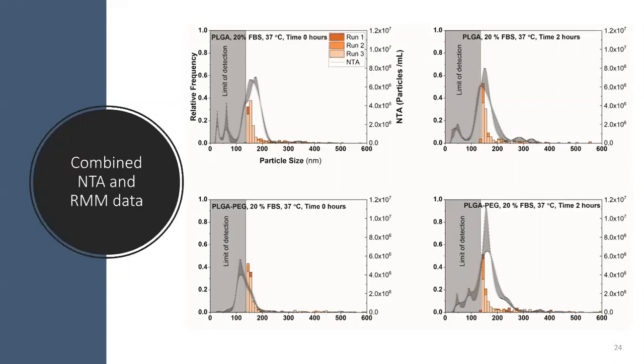And so why is doing this even interesting? As far as we're aware, this is the first time that both nanoparticle tracking analysis and resonant mass measurement have been applied to probe the protein corona that forms around PLGA and PLGA-PEG nanoparticles. And the more data that we have on how nanoparticles behave on being incubated in serum, instead of going, here is my nanoparticle, how does it behave? Eventually we'll be able to go, I want my nanoparticle to behave like this, so what does it need to look like? So essentially reverse engineer the nanoparticles for clinical applications. And then we are more likely to develop nanomedicines which gain clinical approval.